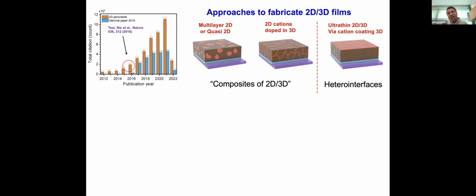Typically, you end up getting an N=1 or sometimes even mixtures of N values. And so you can't really control the electronic transport across these layers. And so typically this approach has limited the thickness of these 2D layers to be really of the order of 2 to 5 nanometers, where you can still achieve transport across these layers, because as you make them thicker, they start to get insulating pretty fast. Okay.